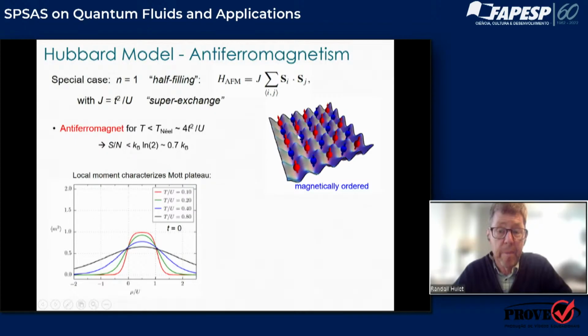And so at that point, you become magnetically oriented. So you get, in a classical sense, up, down, up, down, up, down, checkerboard-like pattern. And you get a local moment, which reflects the fact that the spin states are projected exactly all along Z or anti-aligned with the Z-axis. So this is shown here by this so-called local moment, the magnetic moment squared, as a function of the chemical potential.